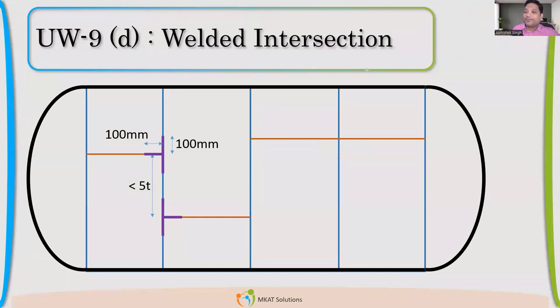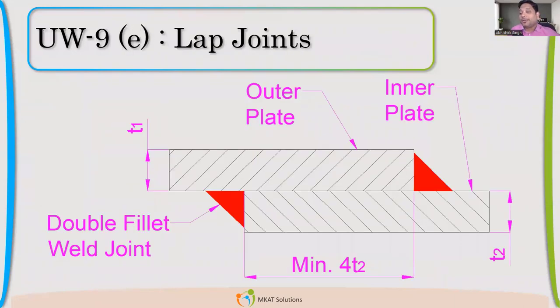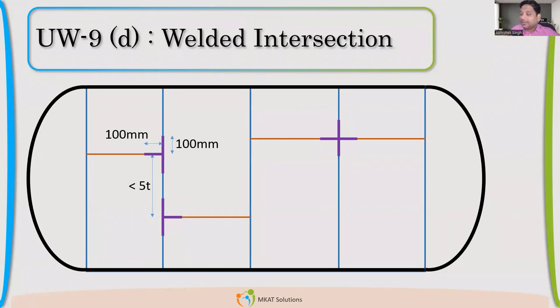So, if we are having a weld like this, then again, we have to follow the radiography requirement of 100 mm all around, and then we can have this weld coming next to each other. But generally, please remember, try to maintain 5T because there will be more welds coming.